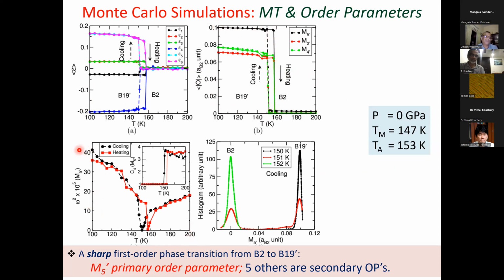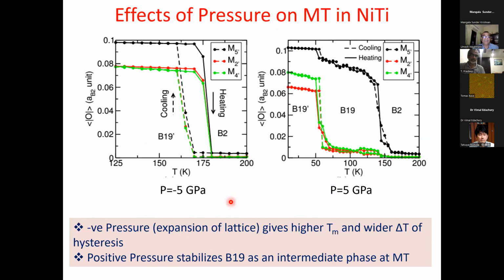If you look at the phonon frequencies of the M5 prime phonon, you will see there is a softening of phonon at the phase transition. Again, the cartoon picture I introduced at the beginning of my talk, that's exactly what we see in this realistic phase transition simulation. And that phonon would have gone down below 0, but because the B19 prime phase stabilizes, you have stable phonons with lower symmetry structure. Okay, so indeed, the transition temperature is greatly underestimated. It's 50% of the experimental value, and we didn't know at that time what could be the origin of this error.